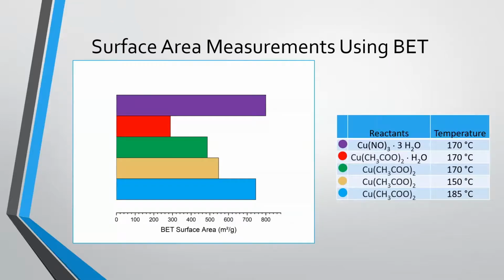The next and possibly more important part of this, compared to our yield, is our surface area. This surface area is important because it's where we are able to hold the different gases and other molecules that get captured. The BET model is an estimation of our surface area by capturing nitrogen gas, and the measurements are taken at liquid nitrogen temperatures and flooded with nitrogen.